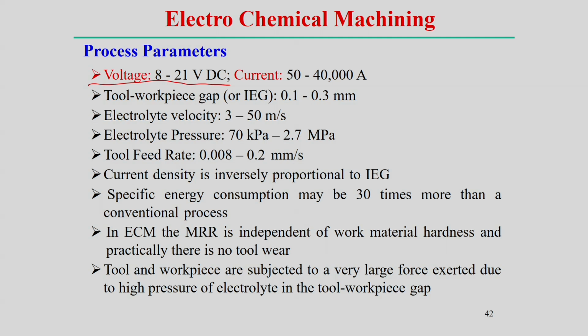Then electrolyte velocity: basically, high velocity electrolyte can be passed through that gap. This can be 3 to 50 meter per second, and high pressure is also created, 70 kilopascal to 2.7 megapascal. That high pressure electrolyte passes through the gap between the workpiece and the tool. And the tool feed is very low.